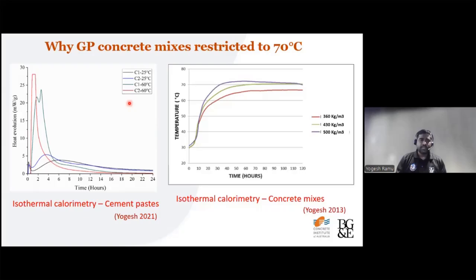But if it is exposed to 60 degrees Celsius, cured at 60 degrees Celsius, you can see the heat evolution is much, much higher. At the same time, it's much accelerated and faster. Because of this faster hydration, it can lead to a lot of coarser hydrate formation in the system. What is coarser hydrate formation? The system is not pore refined really well, so it can be very highly permeable, and it also liberates a lot of heat as well.